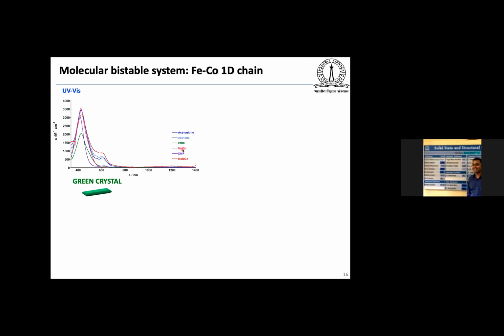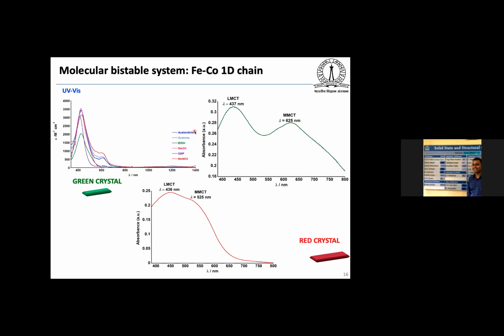And when you measure the solid state UV, you can see the metal-metal charge transfer. We observe approximately the same region, that is 625, and the LMCT is 437. So that means the system is stable in both solution as well as in the solid state. And then when we measure the red crystal, you can see the metal-metal electron transfer is shifted almost 100 nanometers. So that is also very useful information we can get from the UV spectrometer.